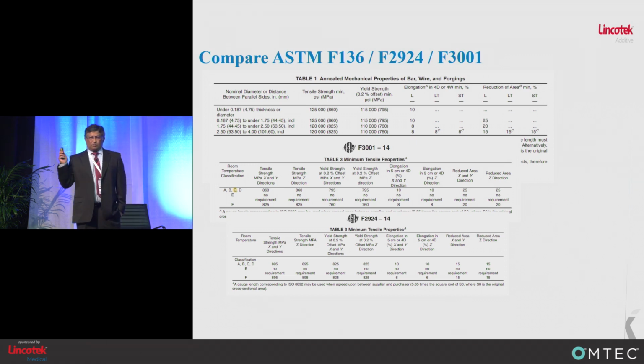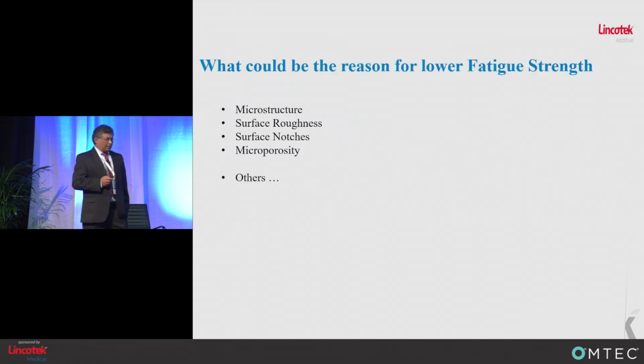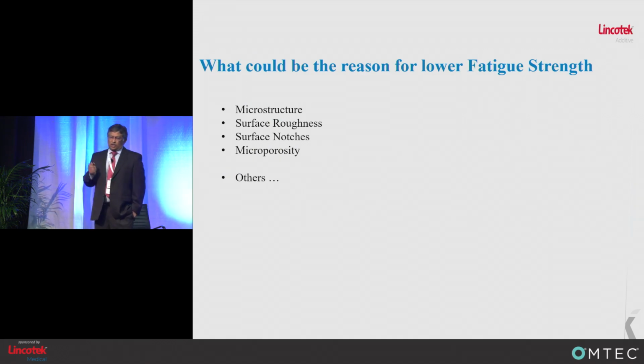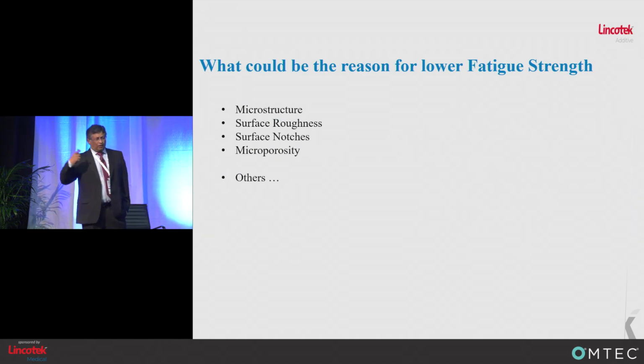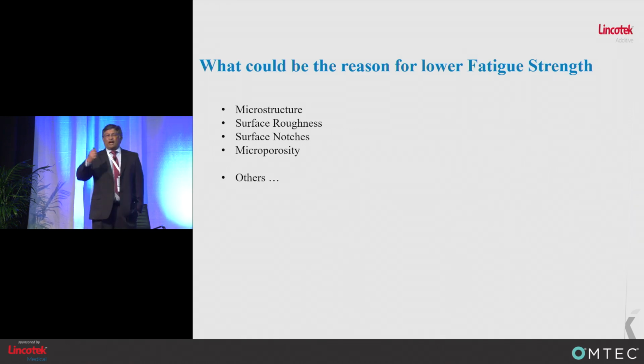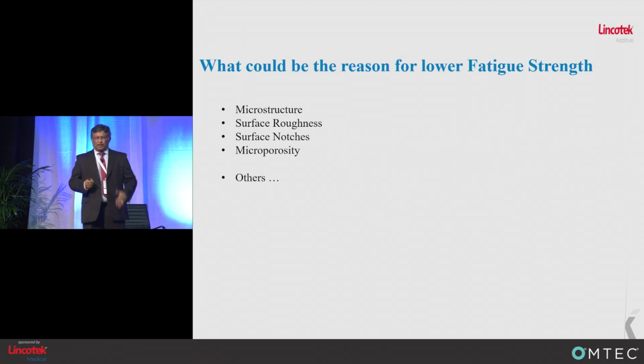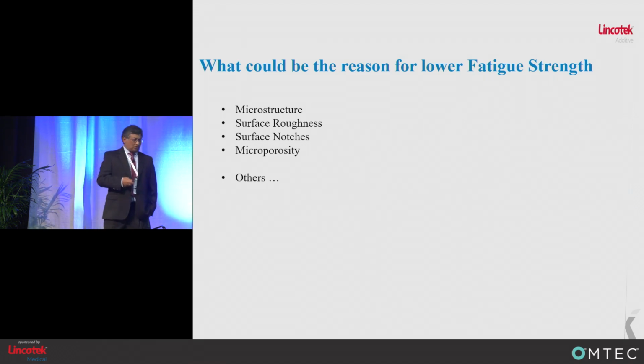So absolutely dispel that. However, I will be the first one to admit, when you're doing traditional fatigue strength tests, rotating beam fatigue strength tests, you will find that it is much lower than traditional wrought material, which may have maybe sinter beads, maybe plasma spray, depending on how the parts were done, right? And that could be because of microstructure, surface roughness, surface notches, right? Microporosity, other things that could happen.